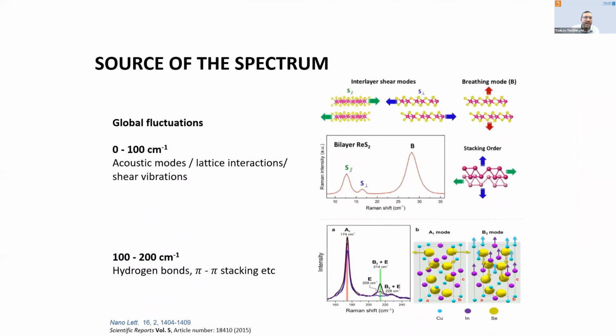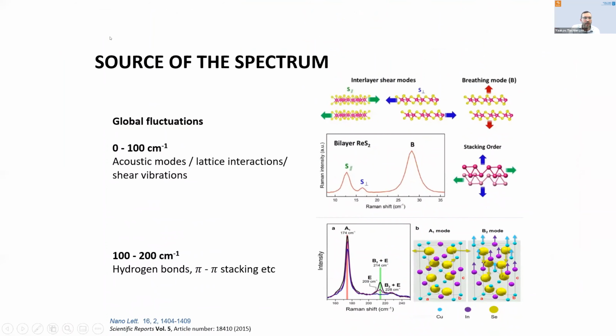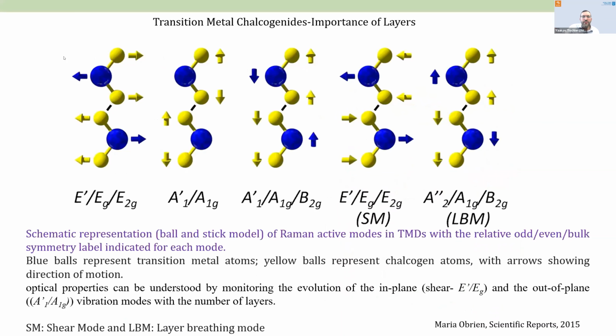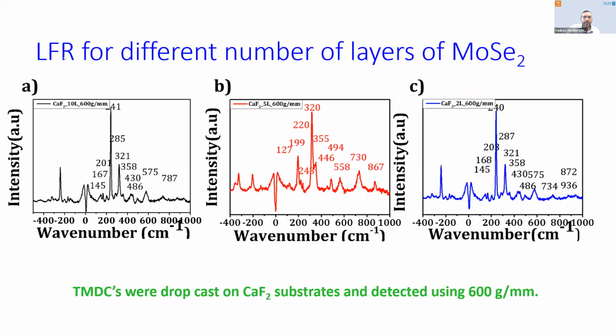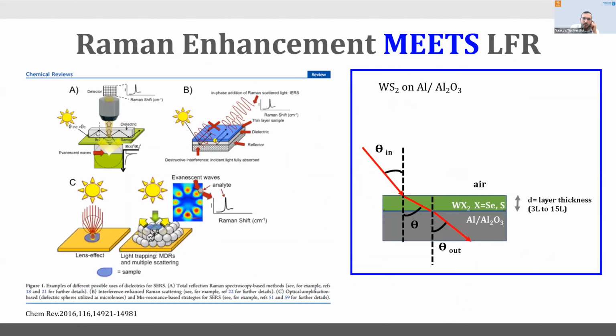Now, how it ties into layered materials is that LFR is very, very powerful by looking at the shear modes or breathing modes. And we've used this now to characterize TMDC type materials. So for example, you need to have a Raman quiet substrate. In this case, we looked at molybdenum diselenide, and you could see, based on the number of layers, differences in the Raman spectrum in the low frequency regime. And let me just say one last thing: